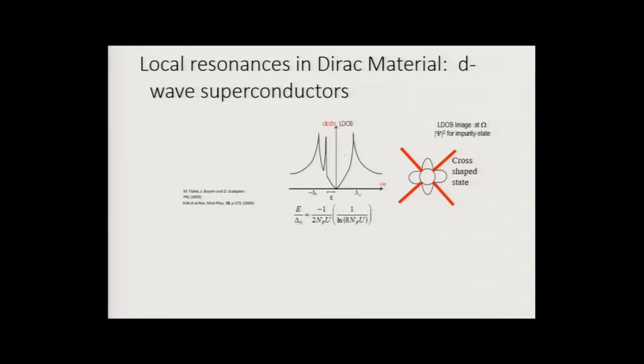concentration of defects, in this case a simple scalar potential of the zinc site on one impurity, then I can look at the scattering of the conduction electrons off the site, and we'll find that this resonance moves in. So in itself, it's very natural. You have a marginal gap superconductor. This gap is not very wide. It's about 50 millivolts in range.